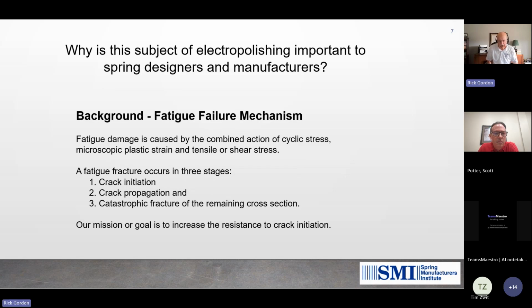So why is the subject of electropolishing important to spring designers and manufacturers? In our Advanced Spring Design class 301 on fatigue, we discuss failures that occur in springs. As we categorize spring failures in our failure analysis work, there's several mechanisms that are involved. But both SMI and others have found that over 50% of failures are due to fatigue. Now, fatigue damage is caused by a combination of cyclic stress, microscopic plastic strain, and tensile or shear stress. As we have learned, a fatigue fracture occurs in 3 stages: crack initiation, crack propagation, and catastrophic fracture of the remaining cross section. Where do cracks initiate?